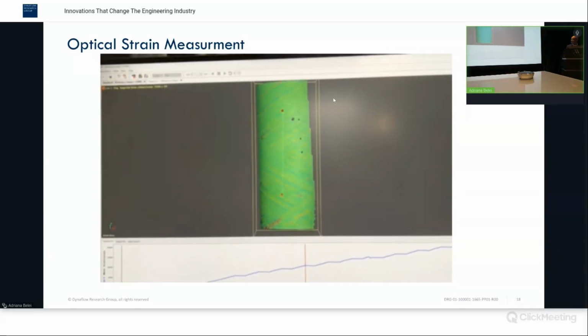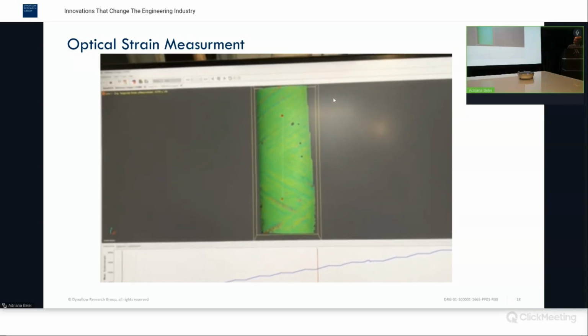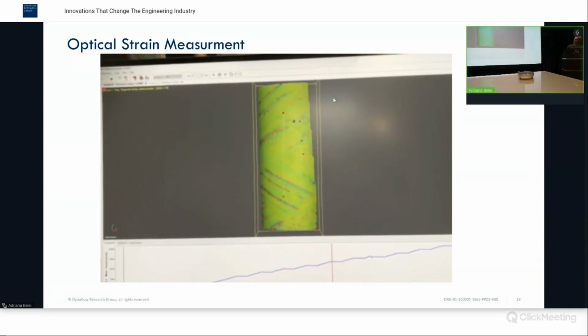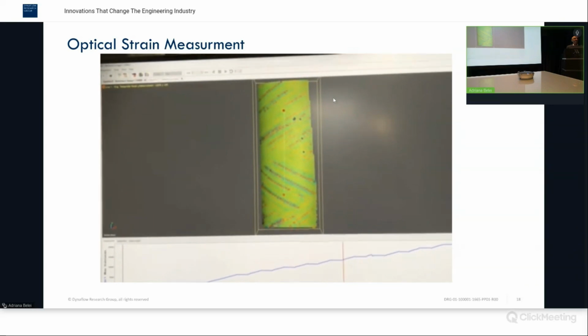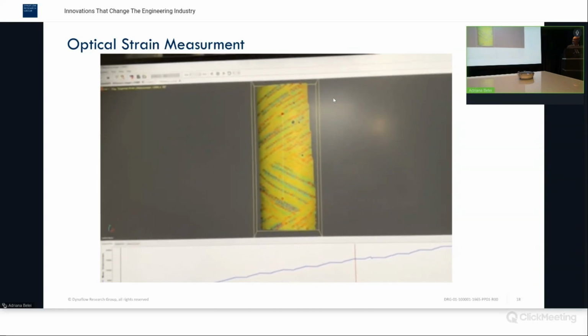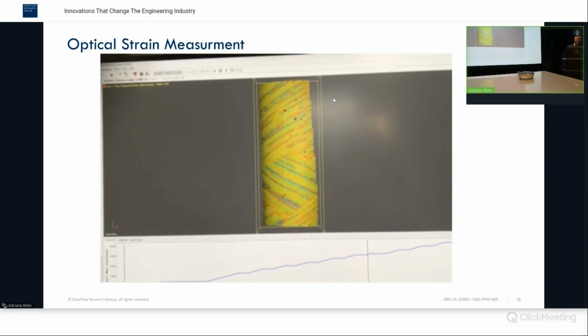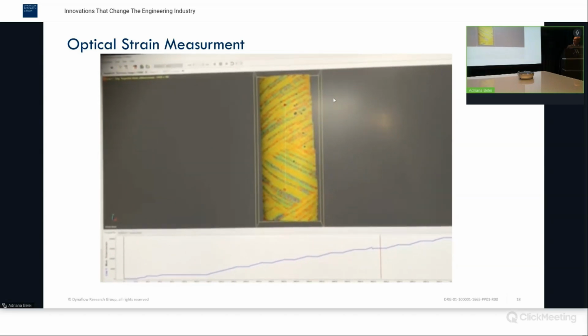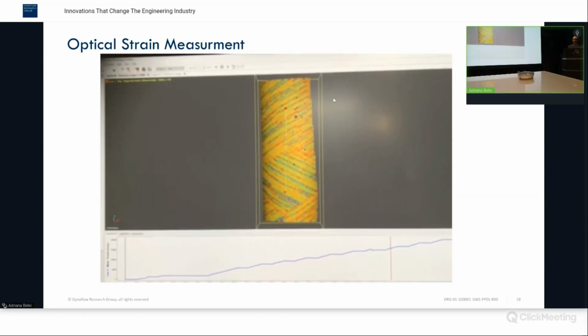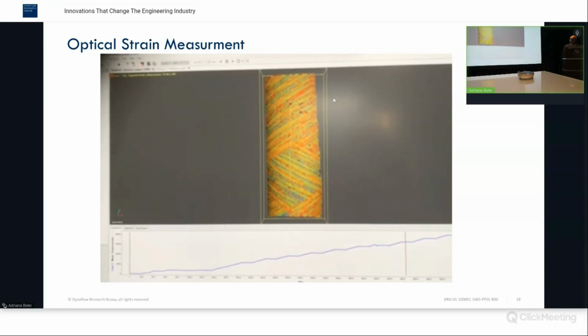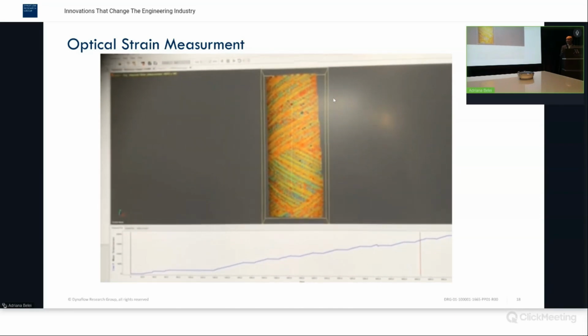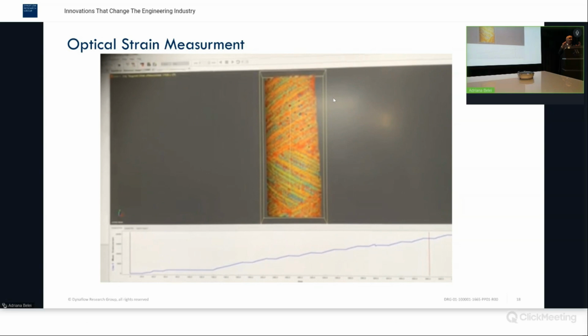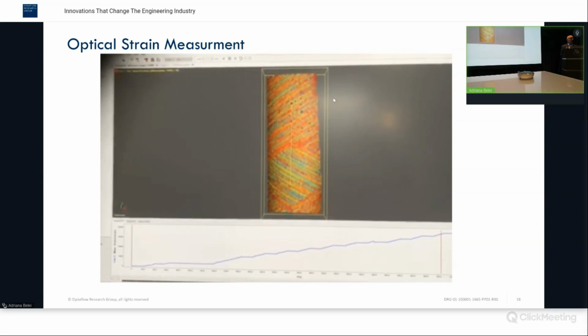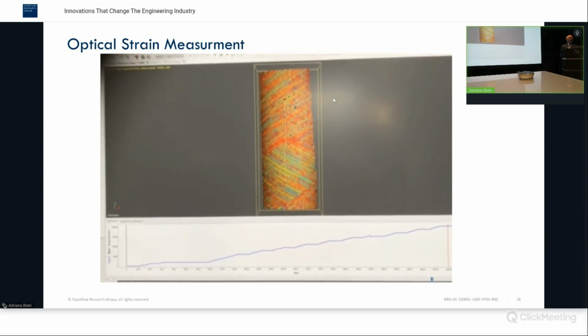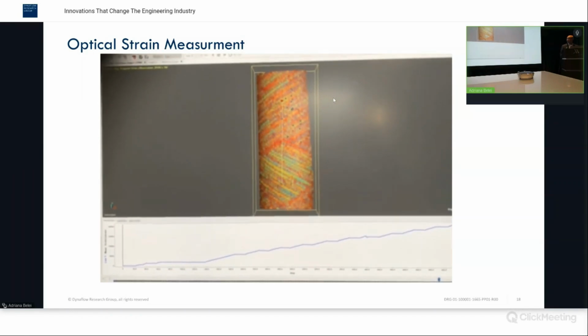And you see that this is a 55 plus minus 55 system. You see gradual development of cracks. So the advantage of optical strain measurements is that you measure the strain over quite a large area. You can do a lot of post analysis.